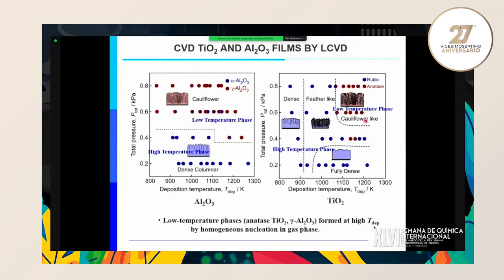So this is how alumina forms in the case of laser CVD as a function of temperature and total pressure. Alpha alumina is the high temperature form, and gamma alumina is the low temperature form. But by CVD, low temperature gamma alumina forms at high temperature, and high temperature alpha alumina forms at low temperature. This is caused by nanoparticles or embryos of alpha alumina forming in the gas phase at first, which become nucleation sites of alumina. So gas phase nucleation is really important.